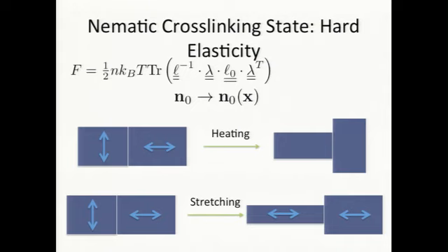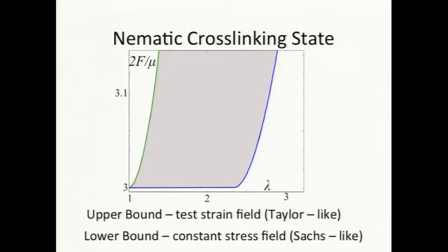I say I expect. I actually don't know how to prove this. If I try and do my same lower bound and upper bound trick, the upper bound actually works perfectly well. The lower bound, as we discussed, I arrived at by throwing out the condition of kinematic compatibility and minimizing over a wider function class. But if we believe it's kinematic compatibility that's preventing it being completely soft, then throwing that out means you lose the effect. So in fact, this is a quite embarrassing set of bounds.